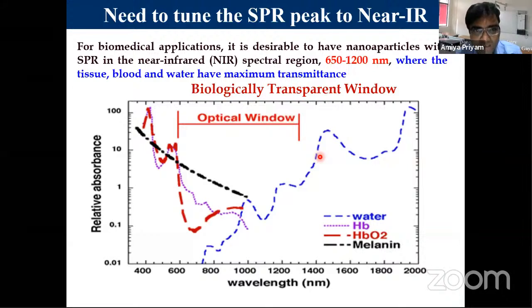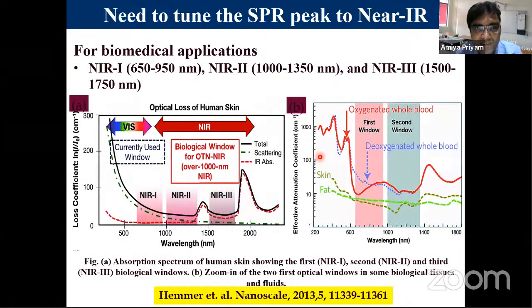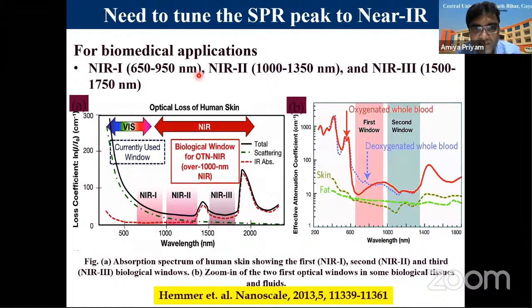So making them non-invasive is the theme, and that propels us to tune the SPR frequency of the gold or silver nanoparticles to this particular region. It has been further analyzed in recent papers that this NIR range, suitable for biomedical application, is further split into 3 sub-windows, NIR 1, 2, and 3, as we can see here: 650 to 950, then 1000 to 1350 nanometers, and then 1500 to 1750 nanometers.